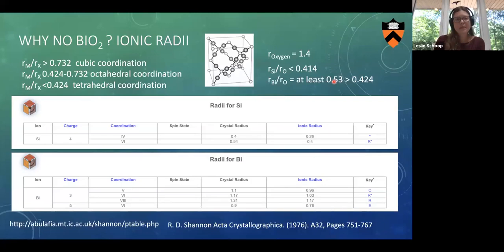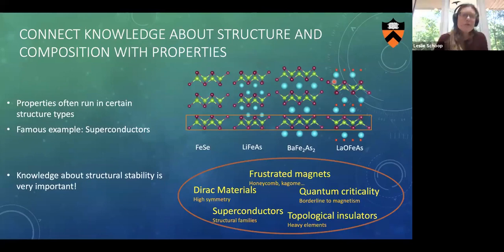Okay, so this is all the rules I want to teach for today about structure. Now I want to talk a bit more about how we connect this to properties. This has been very established in solid state chemistry, that we connect a structure to properties by looking for similar structural motifs and making a connection. An example is that iron-based superconductors all have the structural motif of edge-sharing iron arsenide tetrahedra or iron selenide tetrahedra, and these are all superconductors. So that's great. Once we understand that, we can use our knowledge about structural stability, which is why it's so important, to make more materials with these structural motifs.